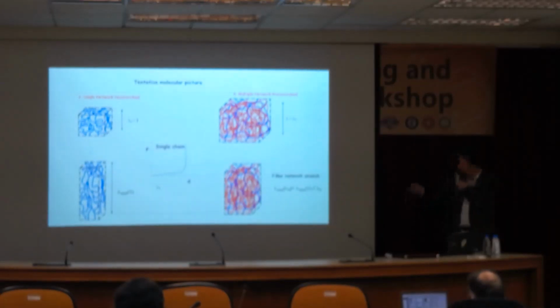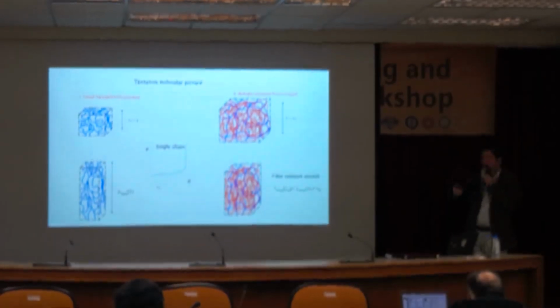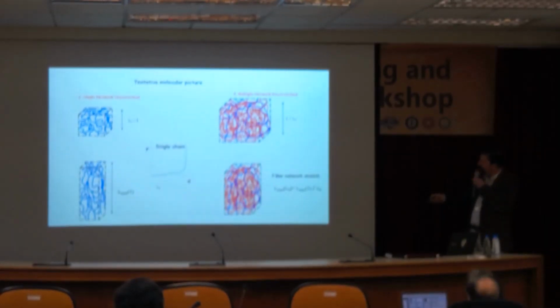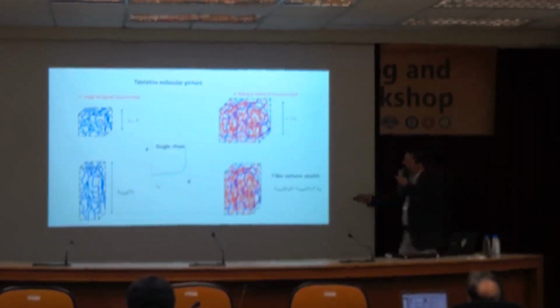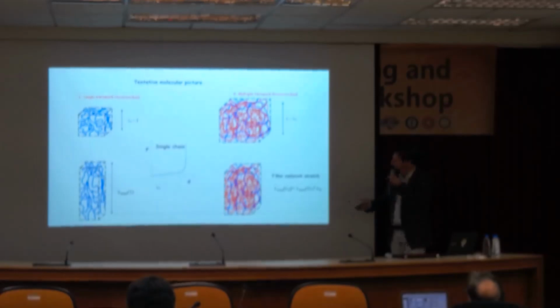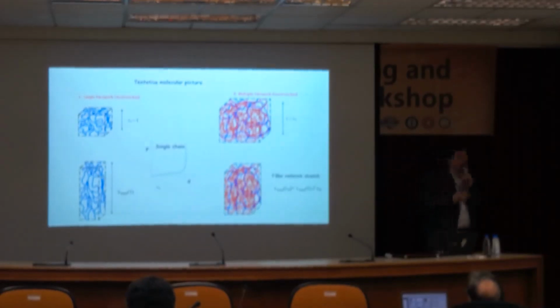If you do a swelling, now your material is pre-stretched, so you're using up some of the stretching, and the maximum extensibility of this material should be less than this one. In principle, it should reduce your maximum extensibility when you go from this to this from the molecular standpoint, because these chains are not pre-stretched, these ones are. Now, is that true in reality?